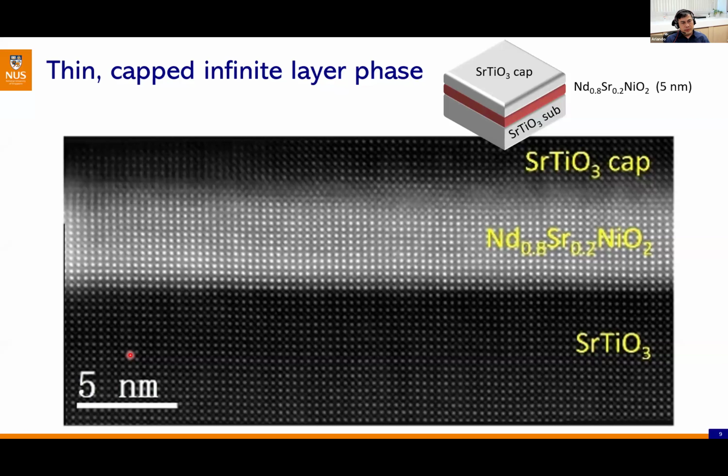If you do the reductions using non-optimized parameters, you will also end up with a non-pure phase and non-superconducting states. The same applies if you have a very good perovskite phase in the initial growth, with very little secondary phase, but don't do a proper reduction: you can also end up with a secondary phase after the reductions.